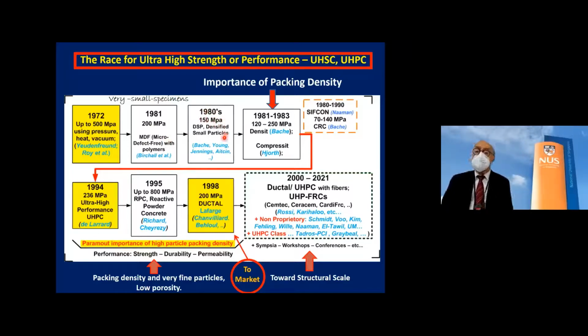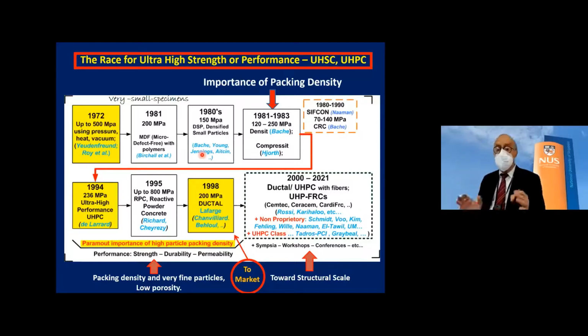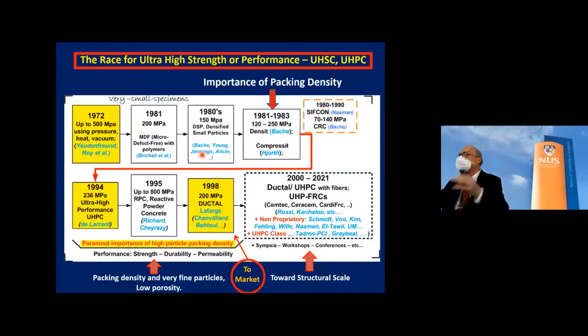In the 1980s, several researchers, and I give names, Bache in Denmark, Young in the US, Aïtcin in Canada, Jennings, were all working on what they called densified small particle cement. For us today, basically cement with something like silica fume added to it to densify the combination, or ground granulated blast furnace slag, etc. Cementitious additives in smaller particles, and they claimed 150 megapascal.